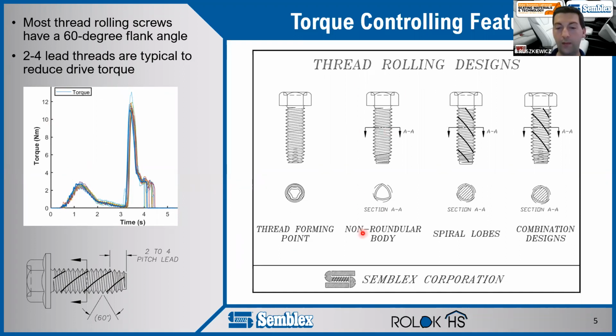If we look at the second image here, this is what's called a non-round body. If we look at the cross section, we see there's 3 contact points. This is called a tri-round fastener. Commercially, this is the Tap-Tite family of products, which is one of the most popular thread forming fasteners on the market. These work very similar to conventional taps. So if you've ever used a tap to thread a hole, you'll notice that you have a threaded region followed by a relief area where there's no threads or no material. So that what you're doing is you're cutting and then you're following it with a relief, and that keeps your torque down and makes it easy for you to use that tap. These fasteners work the same way. You have these points up here, and that's where you're doing most of your thread forming, and then behind that you have a relief to reduce the amount of torque.